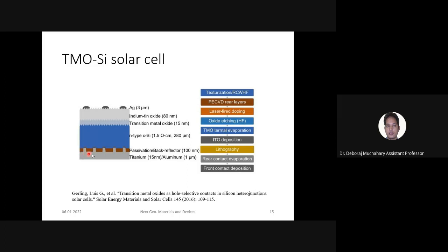They used laser firing to cut some small areas, and only there the contact is made. The contact is not made over the whole area. It is a selected contact they have made. And why this is used is that it will help in reducing the surface recombination. The advantage of this type of structure is that the contact is at these small areas, but at the other positions, it is not directly metal contact. These are passivation layers on top of the silicon surface. Due to that, the surface recombination is very low in this type of design. Since surface recombination is less, the collection probability and all these things are good, and so the efficiency will be high.